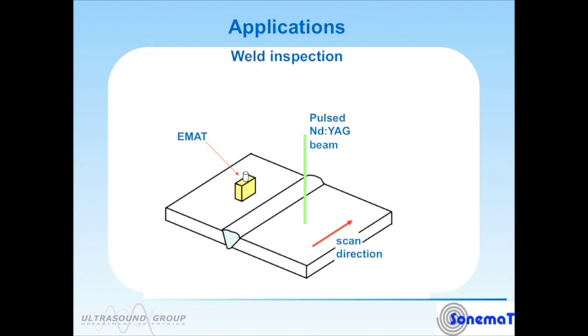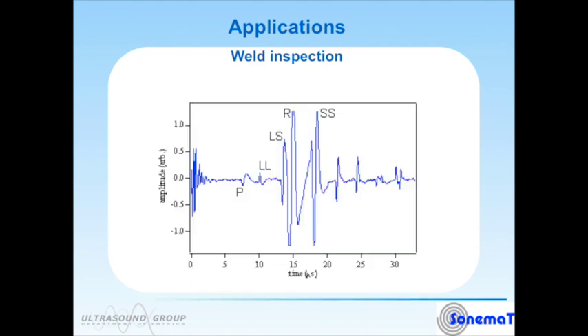Laser EMATs have also been used to do weld inspection. The advantages here are that the system is entirely non-contact and it can rapidly scan across a weld, generating many different modes of ultrasound in one go. If we look at an A scan or a time domain signal for one of these laser shots, what we can see is the P wave is a surface skimming longitudinal wave, the LL wave is a longitudinal wave reflected from the back of the weld, the LS is a mode conversion of a longitudinal to shear, the R is a Rayleigh wave, and the SS is a shear wave that's reflected from the back of the sample. And they're all different kinds of combinations and permutations of waves that reflect and mode convert, but they appear as a discrete set of spikes.